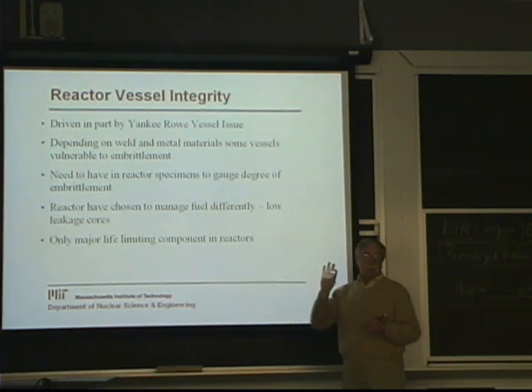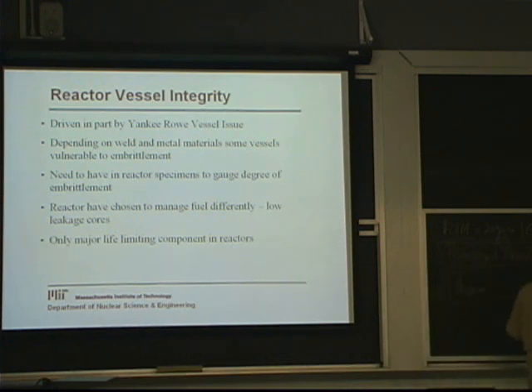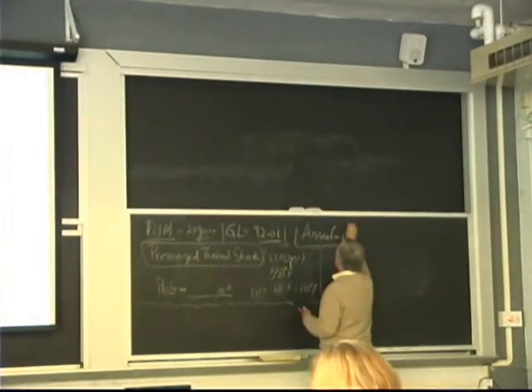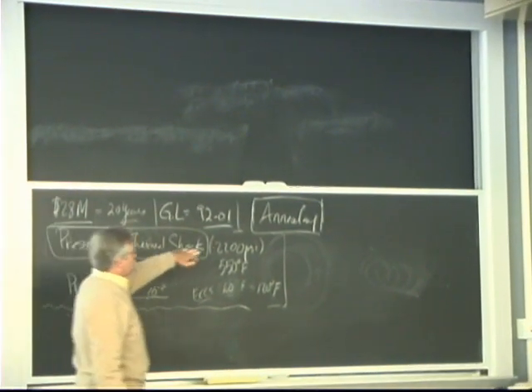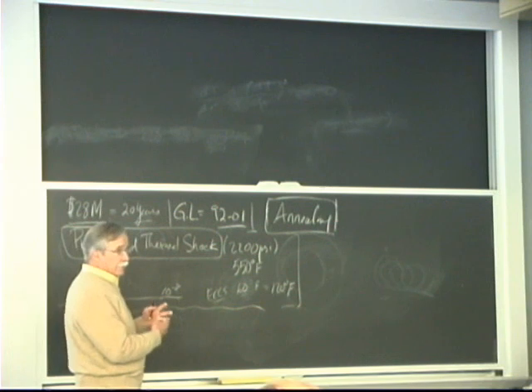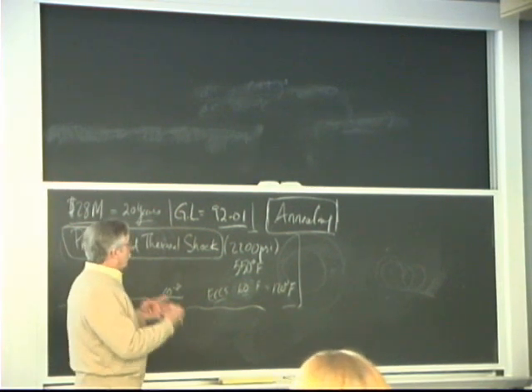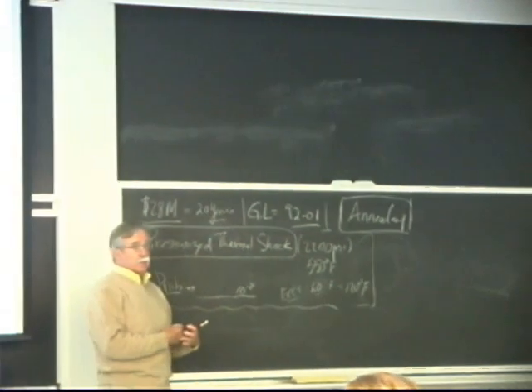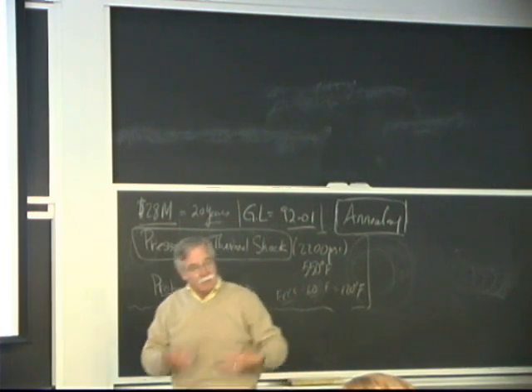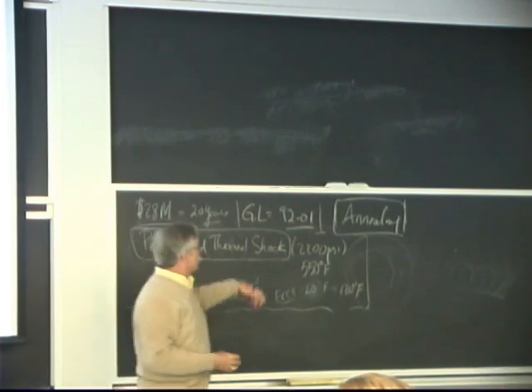The other thing that you can do with this is called annealing. And we looked very hard at this concept of annealing. It has been done in reactors, I believe in Russia for sure, and I think in a Belgian reactor. Annealing is basically heating up the reactor vessel welds, or those zones where you have potentially embrittled conditions, and allowing the material to relax and restore some of its original properties. And this annealing could potentially allow you to get 10 more years of operating life and then allow it to re-irradiate. So annealing is another solution to reactor vessel integrity issues if replacement is not an option.